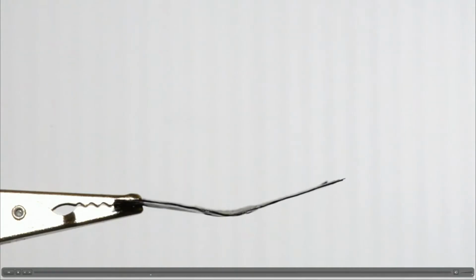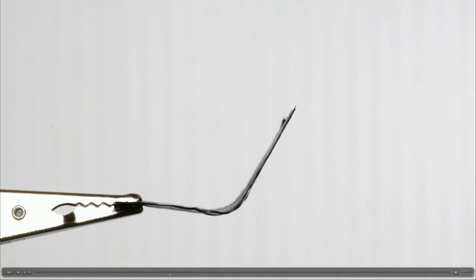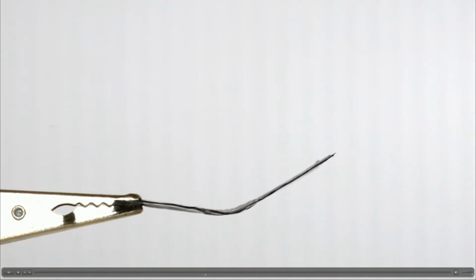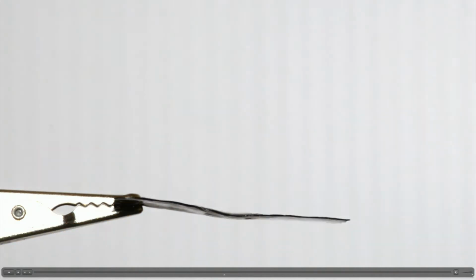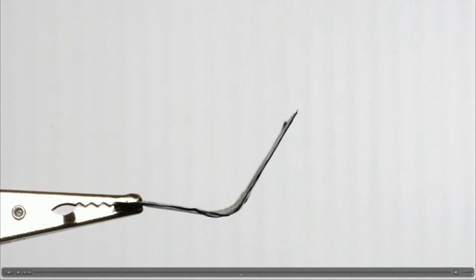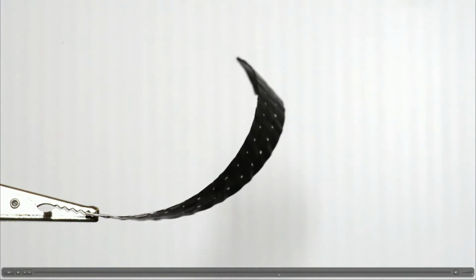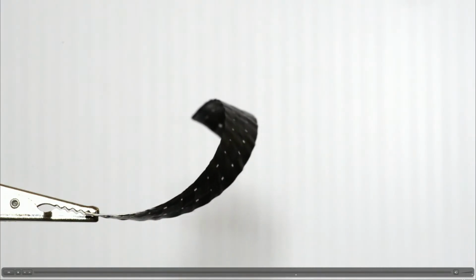So another material is composites. We worked with a company called Carbitex who makes fully cured but flexible carbon fiber, and we print or bond or spray or laminate on top. So we take this flexible carbon fiber, we combine it with different polymers. The polymer is going to respond to some activation energy, like moisture we've already shown, temperature, light, so we can change that composition. And then the grain pattern that we print will create the fold or the curl. So we can control the angle or the behavior of the material.